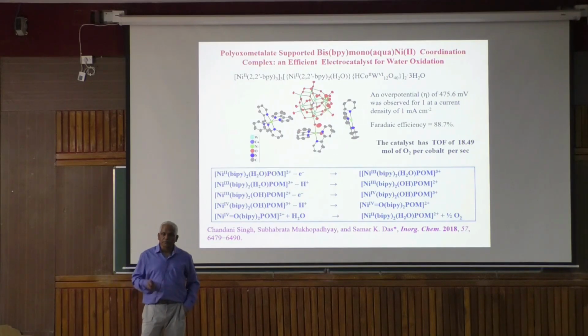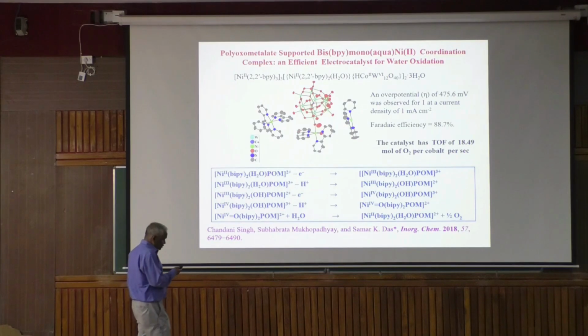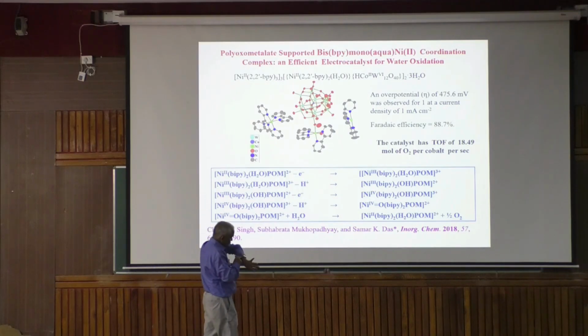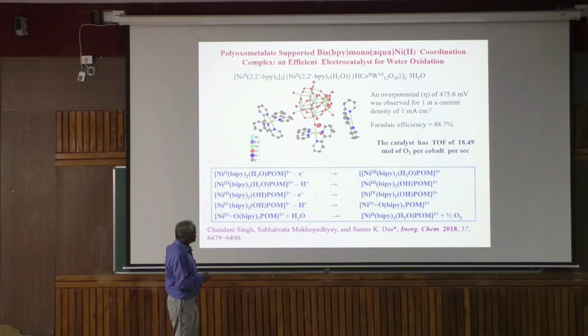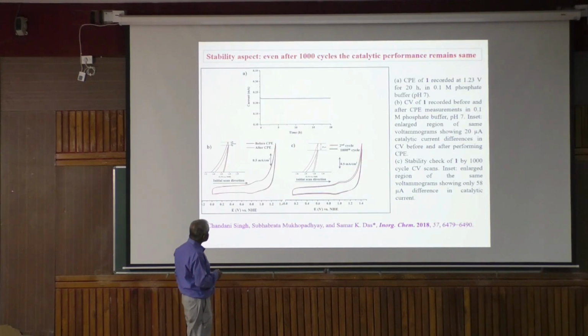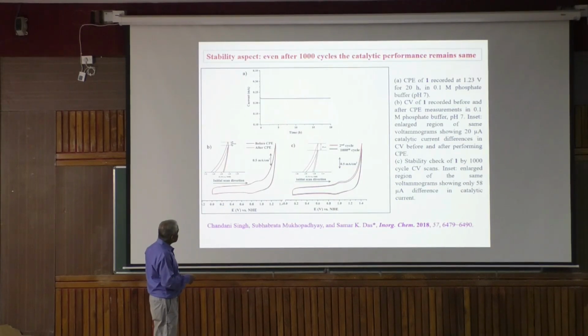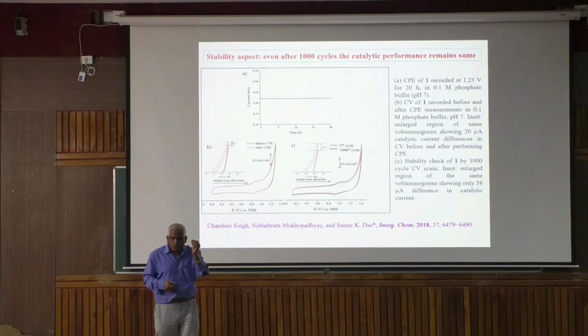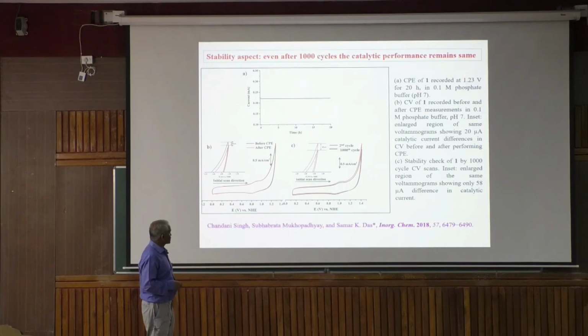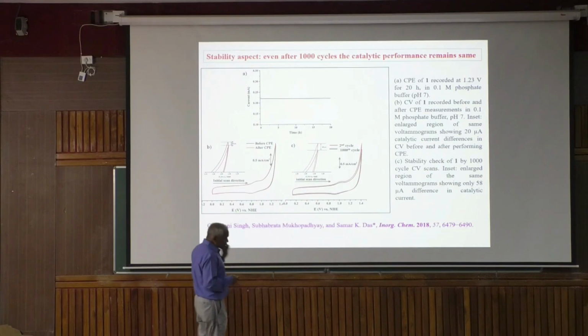It will give bubbling of oxygen, and again we got very interesting parameters, like what we wanted to have. Faradaic efficiency close to 90%, very good turnover frequency, and I must say a very good, decent overpotential. You can make it cycle. We also did the CP and cyclic stability to 1000 cycles. It is almost the same, a little bit different because oxygen gas comes out. That's a little bit different in time. So you can do it like that. Very interestingly, the nickel compound gives water oxidation.